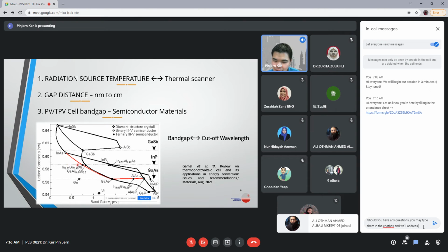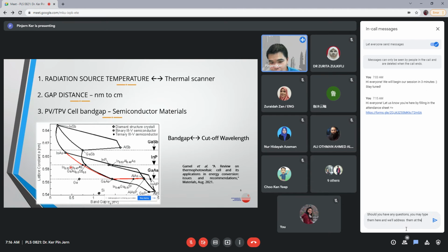And we also look at other types of indium gallium arsenide and indium gallium arsenide antimonide to push the band gap of the semiconductor into an even narrower region, so that we can harvest photons all the way up to about 3000 nanometers. And that is the difficulty that I mentioned earlier in the first introductory slides.